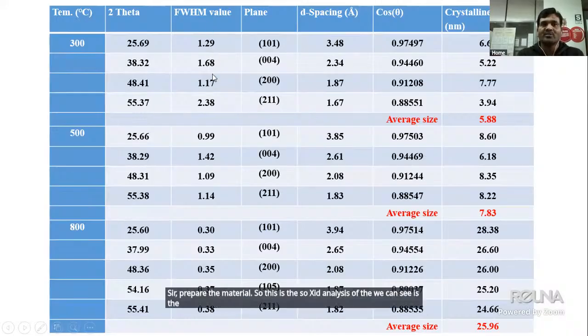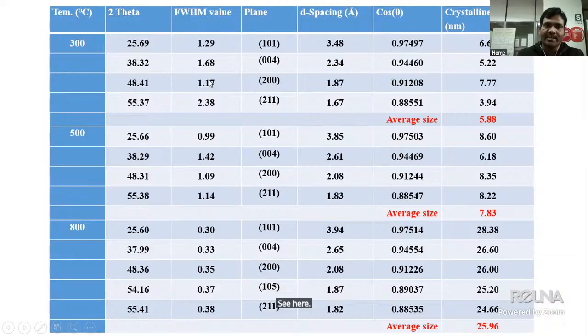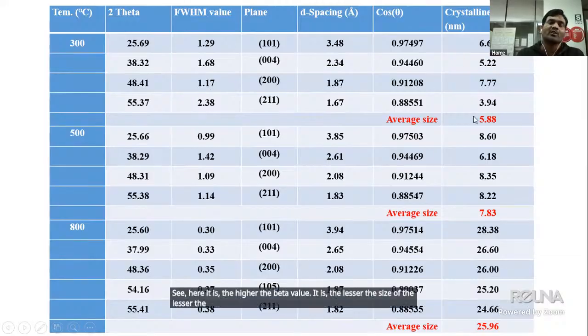So this is the XRD analysis. We can see the full width at half maximum. We can see the smaller the beta value, the higher the size of the material. Here the higher the beta value, the lesser the size of the material. So the XRD analysis of the three materials, 300, 500, 800 degrees, identifies the crystalline size of the material.